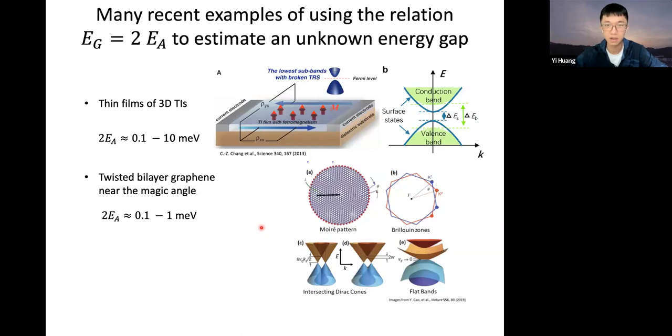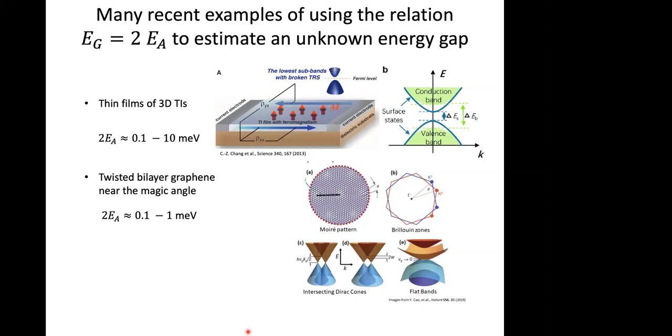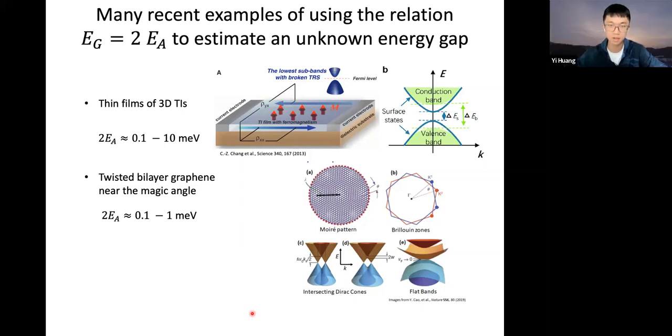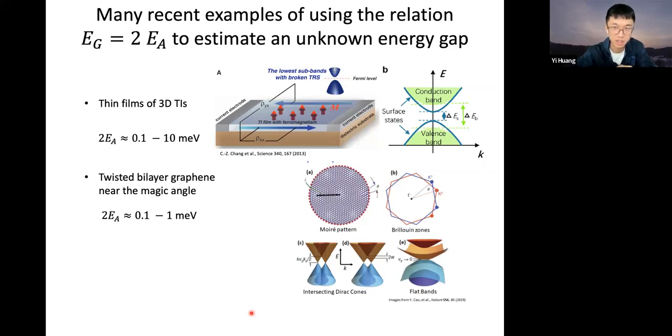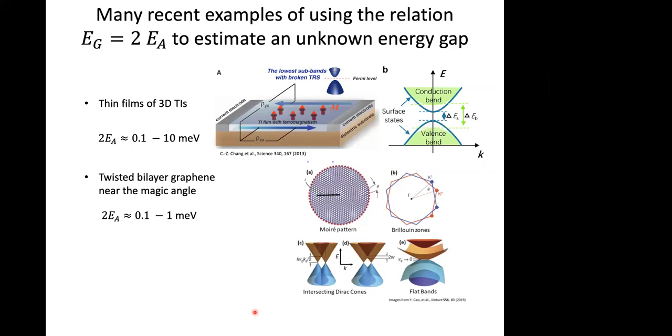Oh, I see Ilya has a question. Hi, is it okay to ask questions right now? Yeah, sure. My quick question is the following: in a realistic semiconductor, which is doped by any amount, you would have tail states, and then any measurement of any gap would probably tell you more about the mobility gap than the band gap. It's a classical mobility edge. Is this going to be relevant for you? The tail states can change this energy by a lot. That's actually used in some lasers. Semiconductor lasers use this mobility gap instead of the band gap to produce light.